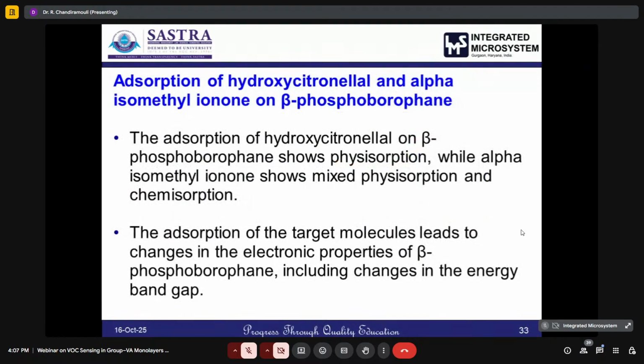And here are some of the vapors evolved from the cosmetics. We have chosen two target vapors, hydroxycitronellal and alpha isomethyl ionone, that are evolved from the cosmetics. The adsorption of hydroxycitronellal on beta phosphoborophane exhibits physisorption, by the weak van der Waals forces. Whereas the alpha isomethyl ionone shows a mixed physisorption and chemisorption.